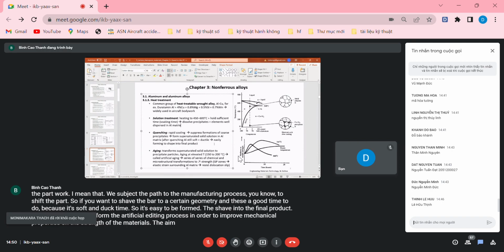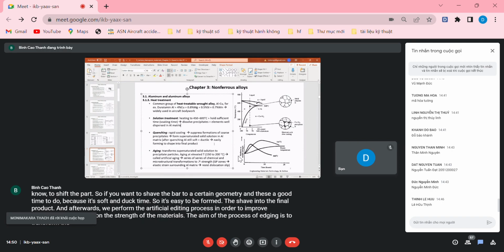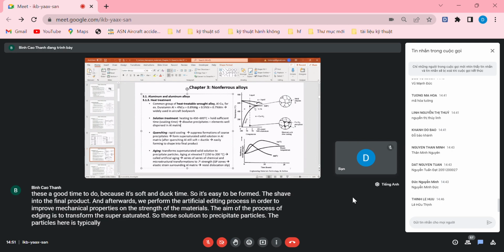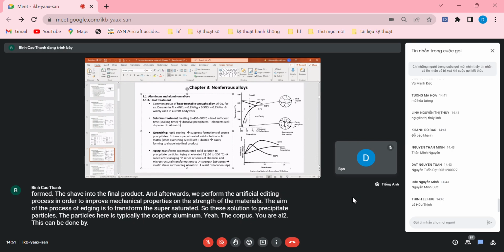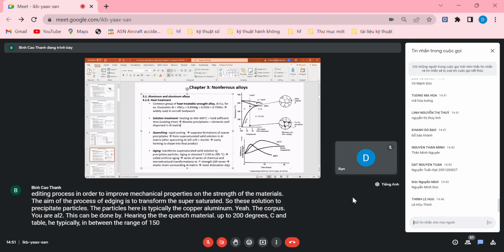The aim of the aging process is to transform the supersaturated solid solution to precipitate particles. The particles here are typically copper aluminide, CuAl2. This can be done by heating the quenched material up to 200 degrees C, typically in the range of 150 to 200 degrees C.